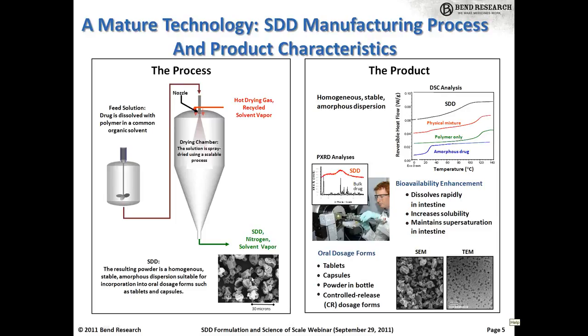And again, when done right, you have a homogeneous, stable, amorphous dispersion, which can be evidenced by thermal analysis like differential scanning calorimetry to have a single glass transition temperature. No evidence of crystallinity by powder X-ray. Again, when executed with the right polymer, the right drug-polymer ratio, and the proper manufacturing, the advantages you get for poorly soluble drugs are rapid dissolution, increased solubility relative to crystalline forms, and maintained supersaturation, or maintaining that increased solubility in the intestinal fluid. And so as such, you get increased absorption of a poorly soluble drug. And then SDDs can be included in a number of dosage forms, which we'll discuss more in a few slides.